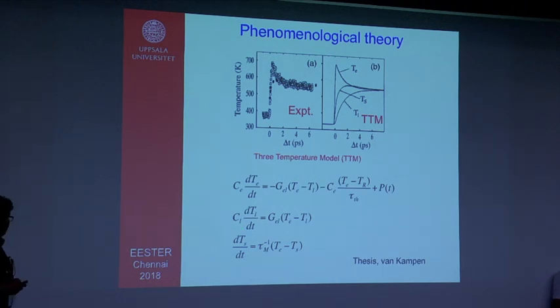And then you solve them, and then you find out how the temperature actually behaves with time, delta T, that is the pump probe delay time. So this is the experimental profile actually. This is actually measured in experiment. And if you follow the 3-temperature model, if you simulate it, you get a profile also like this, which is very nice. But that is the profile for the electron temperature.